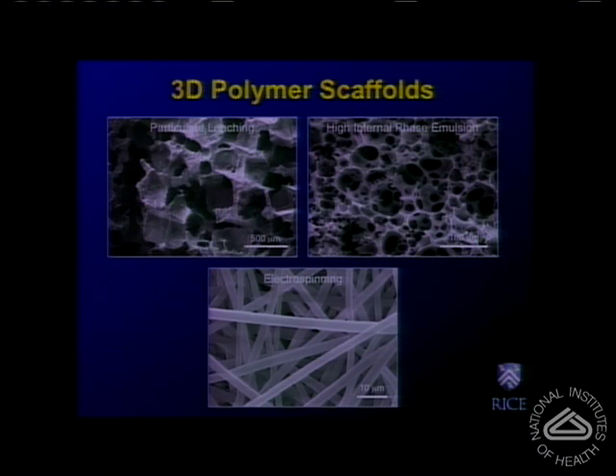There are myriads of processing techniques that one can use, again, to fabricate three-dimensional scaffolds with controlled physicochemical properties as needed for different applications. And the two most important properties of these scaffolds have been the pore architecture as well as the degradation properties. We and others over the years have shown that the pore architecture can be used to modulate the differentiation of cells and also the generation of a new tissue. And the degradation properties are very important as one is trying to match the degradation of the scaffold with the regeneration of a new tissue and the deposition of extracellular matrix.